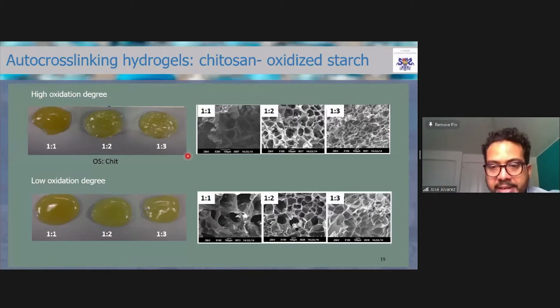All right, thanks. So we did a lot of research on the oxidation degree, the composition of the hydrogels. We found that the hydrogels were indeed cytocompatible. However, when we tried compatibility of the components of the hydrogels alone, the high oxidation degree starch caused cell death. So we decided that this was not suitable for biomedical applications, but low oxidation degrees and medium oxidation degrees work really well.